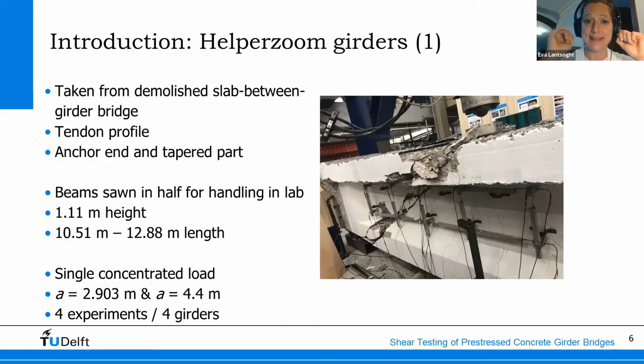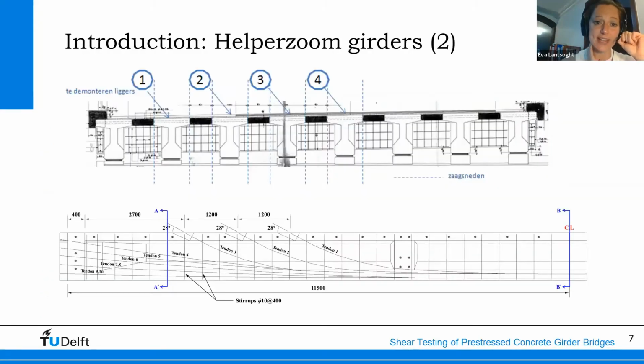We tested 4 of these specimens at two different positions of the concentrated load: at 2.9 meters from the support and at 4.4 meters from the support. So 4 experiments on 4 different girders. Here you can see the 4 girders that were taken from the bridge. So this is a cross section of the slab between girder bridge. So you see how the slab is indeed cast between the top flanges of the girder.